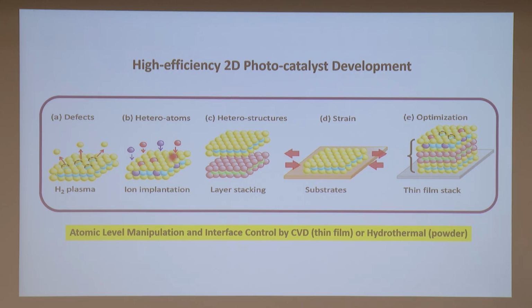And one particular method is to generate defects. In this case, it is sulfur vacancy by hydrogen plasma treatment. You just knock off the sulfur atoms. And you can also incorporate dopant atoms, okay? You can incorporate them by chemical-based methods or by ion implantation. And you can also build heterostructures layer by layer, or with strain effectively produced by utilizing different substrates. And maybe you can mix all these together.